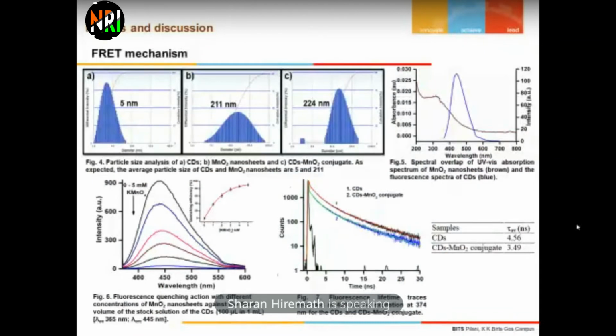Next you can see figure 6, where after addition of KMnO4 the fluorescence intensity of the CDs is gradually decreased, and we have reported around 80 to 87% quenching of the CDs on addition of KMnO4. And now, to understand whether the quenching is static or dynamic, we have carried out